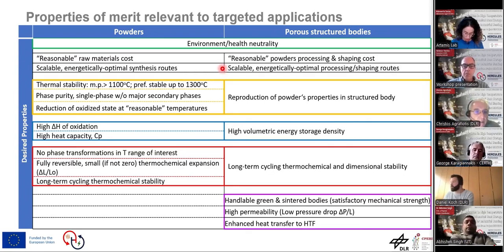As we said before, we need our compositions to have thermal stability, to have a melting point above 1100, preferably up to 1300. And as we mentioned, we need phase purity, single phase, no secondary phases. And as we discussed about some systems, these systems have to be reduced at reasonable temperatures. And of course, we need to reproduce all these properties from the powder to the porous body. The fundamental properties of merit, as was stressed, are the heat of oxidation and the heat capacity. One is a measure of the sensible heat, the other of thermochemical. Together, they give us the hybrid sensible thermochemical storage capacity of the materials, which of course we want to maximize.